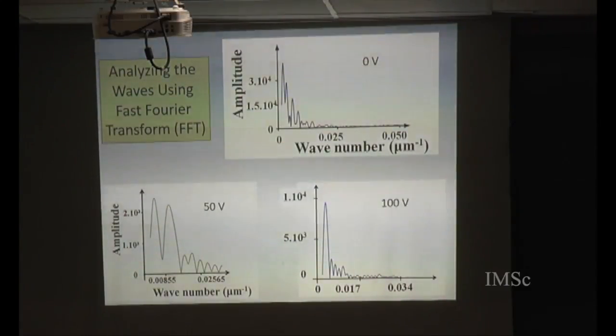Now, the result is like this. For 0 volt, one of those contours analyzed gave this kind of result. Here you see that there are 1, 2, 3, 4 peaks which are quite prominent, which correspond to 4 different wavelengths. And this part you can discard as noise. And at a higher voltage of 50 volt, there are 2 prominent peaks corresponding to 2 wavelengths. But for 100 volt, there is only 1. So apparently, this is just one pure sinusoidal wave.